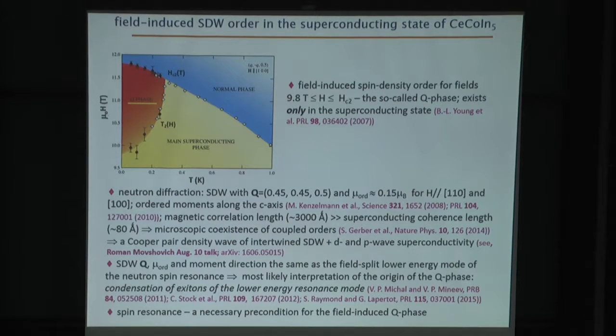The point I simply want to make today is that in this Q phase, this magnetic order has the same ordering wave vector, essentially the same ordered moment, and the orientation of those ordered moments is along the z direction. And this is precisely the same conditions that we know exist in this field-split low energy mode of the spin resonance. And so this suggests that this spin density wave order arises from the condensation of excitons in the spin resonance that was predicted by Michal and Mineev. So assuming that interpretation of the origin of the spin density wave is correct, then in fact the existence of a spin resonance in the superconducting state of cerium cobalt indium-5 is a necessary precondition for the existence of spin density wave order in the superconducting state of cerium cobalt indium-5.